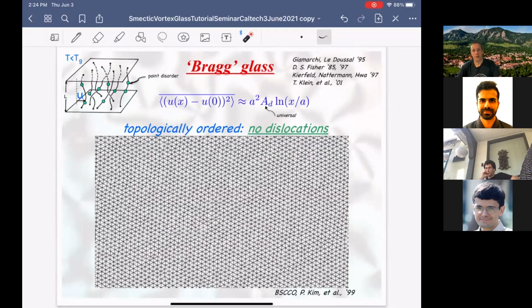A real question of principle arose. This was first brought to everybody's attention and explored extensively by Giamarchi and Le Doussal, and that is the existence of the so-called Bragg glass, which one can think of as a topologically ordered glass of vortices, or more generally, a random field XY model, where there are no topological defects. In the context of vortices, it's no dislocations. So the question of principle is, if the disorder is sufficiently weak, is it possible to have a randomly pinned elastic medium or a randomly pinned vortex lattice that forms a glass, but that glass is topologically ordered, in the sense that although it's distorted elastically, it has no dislocations.